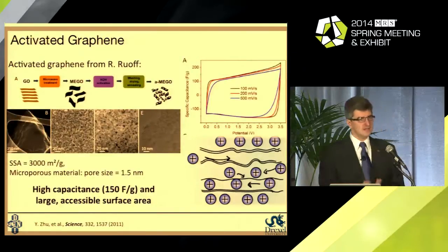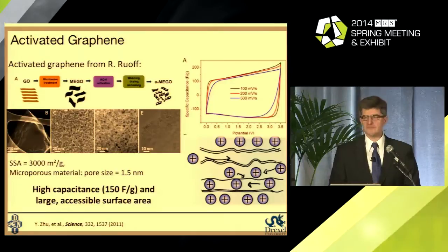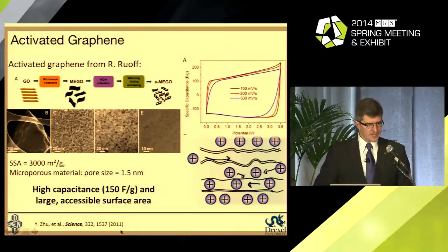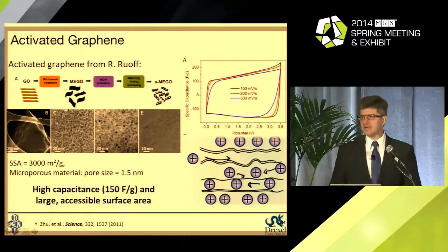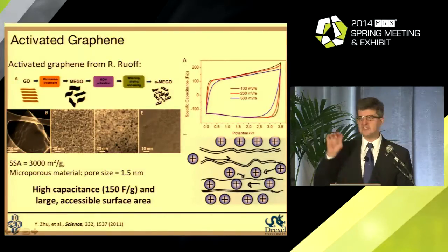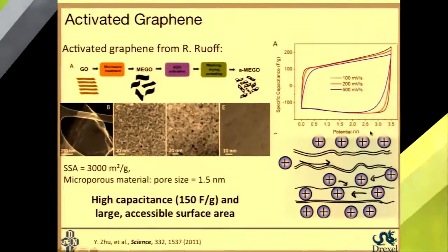However, activated carbons that people use nowadays have specific surface area about 1500 square meter per gram, while carbon nanotubes or onions have just a few hundred square meter per gram surface area, naturally giving a lower capacitance. However, here we also have graphene, for which theoretical specific surface area for a single sheet of graphene is 2600 square meter per gram. And Rod Ruoff published a couple of years ago a paper reporting on activated graphene. They called it aMEGO, activated microwave exfoliated graphene oxide. So this is like graphene with drilled holes with high specific surface area, showing actually pretty good performance at room temperature in ionic liquid organic electrolyte.